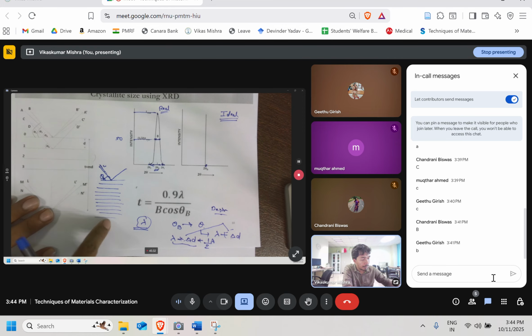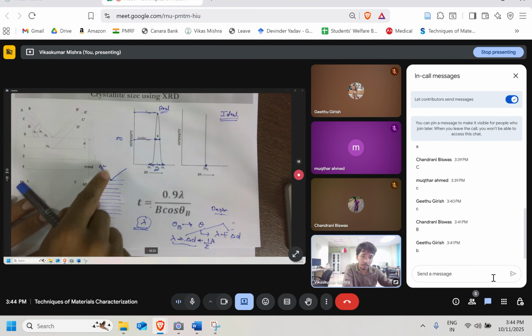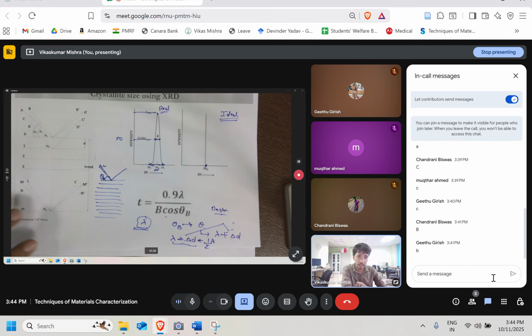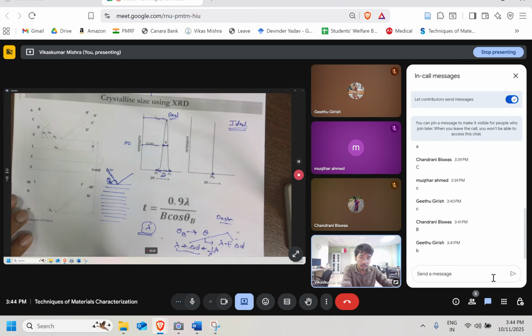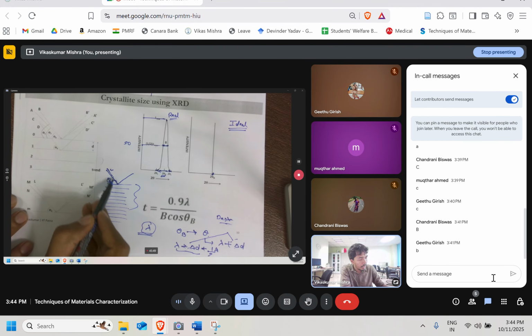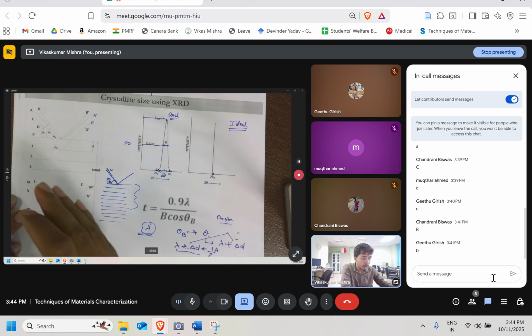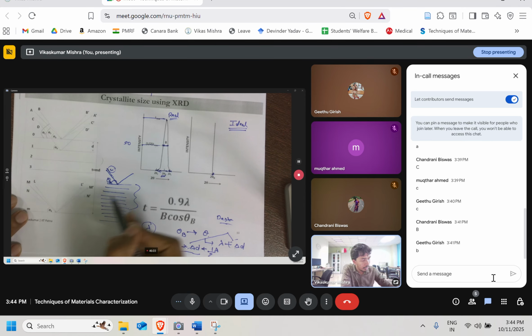So destructive interference will happen for any theta which is away from the Bragg angle. Now for the real crystal, the problem is that the number of planes is fixed. Initially, when we were moving away from this particular Bragg angle, we were able to find the plane that destructively interferes, but it had to search quite far down. In this case, the number of planes itself is fixed, let's say only this many planes are there.